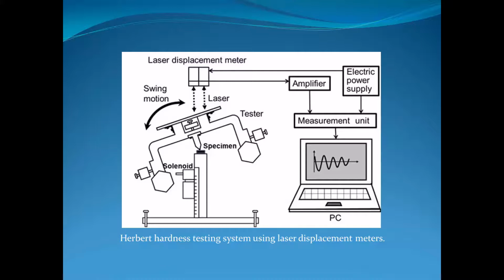Before conducting a test, the device is tilted horizontally up to 30 degrees. A solenoid switch maintains this initial tilt angle. Then the switch is released by retracting the plunger relative to the main body of the solenoid. The device then starts to freely undergo damped vibration on the test specimen.